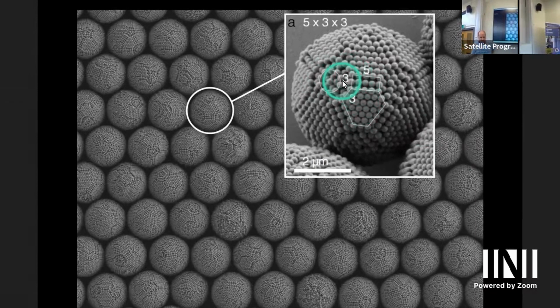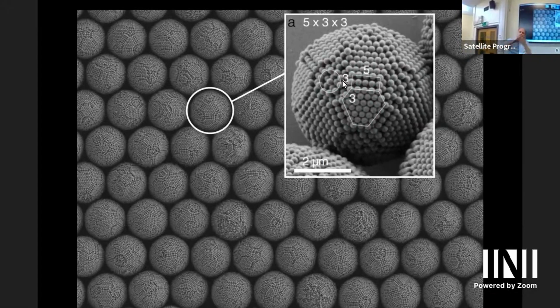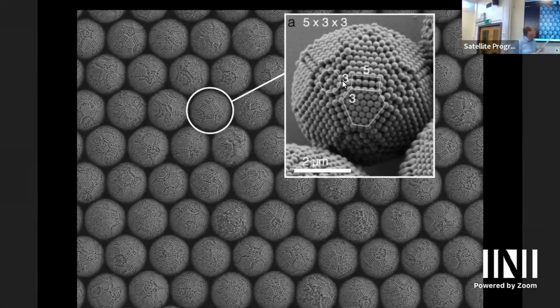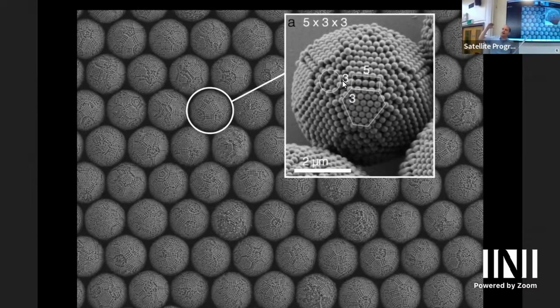And this one is actually a generalization of a Mackay cluster. This is called an anti-Mackay cluster. So what you do is you start forming the Mackay layers in an FCC fashion, and you introduce an HCP stacking fault. Then you continue with FCC to the outside. And you can show you can only introduce a stacking fault exactly once. You cannot do it more for geometric reasons. And this gives us the anti-Mackay classes. By counting the geometry of these rectangles, we can say how many Mackay layers and how many anti-Mackay layers we have. I will show you this in a second.